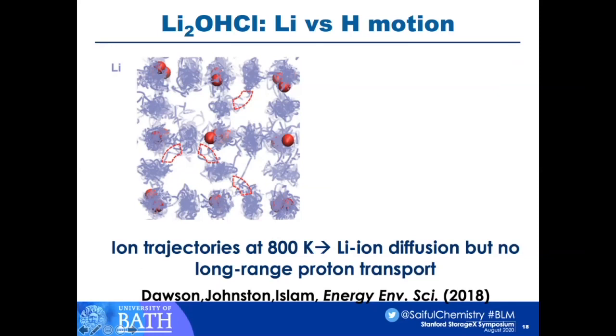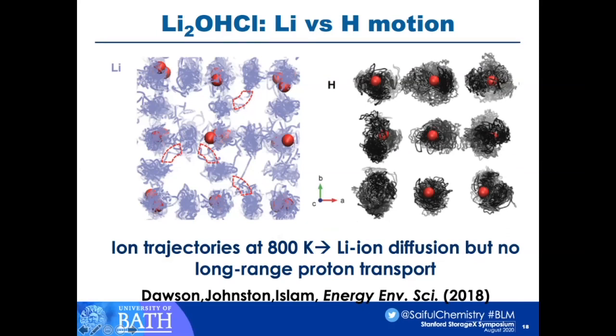So on the left are the ion trajectories of lithium around the red oxygens. I don't know if you can see, but you can roughly see some octahedra around the oxygens where the lithiums are largely located. In red, or these red dots, I've highlighted some lithium vacancy hops along the edge of the octahedra. So there is lithium diffusion. However, on the proton side, and this is the proton in black, you see just rotational motion around the oxygen. So there's no real hopping between the oxygen sites. You can see it's very much localized around the oxygen. So you're getting these OH rotations. And this was published in Energy and Environmental Science in 2018.